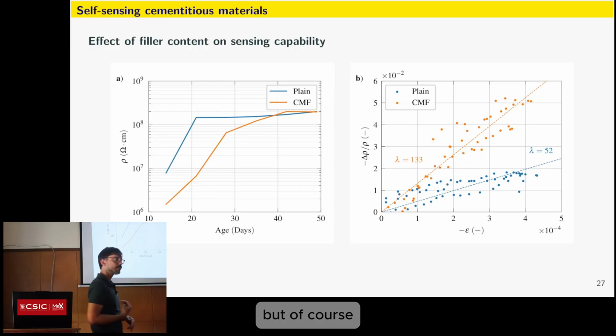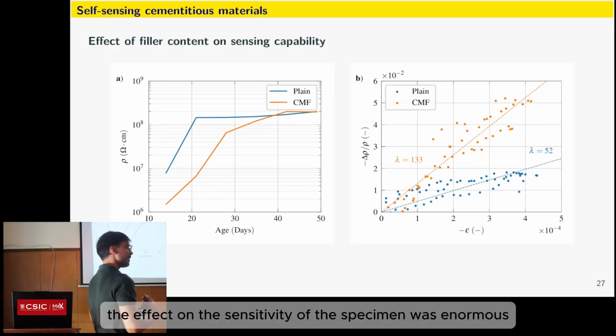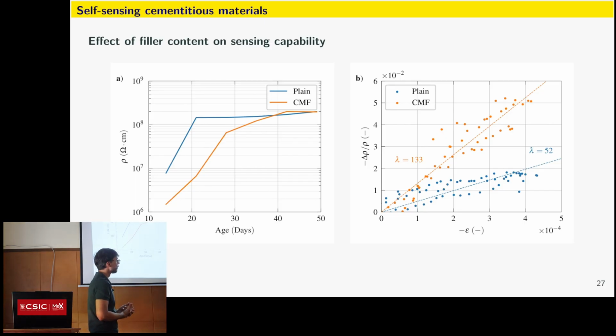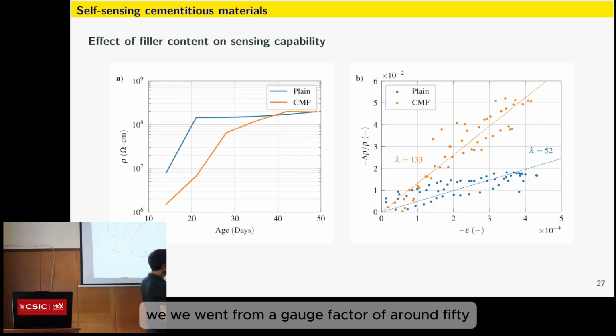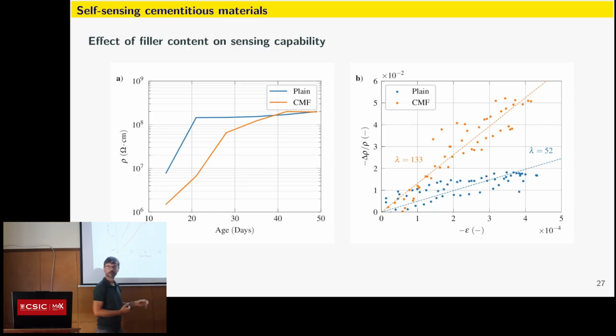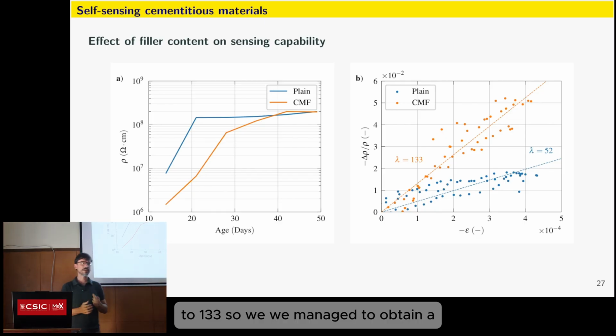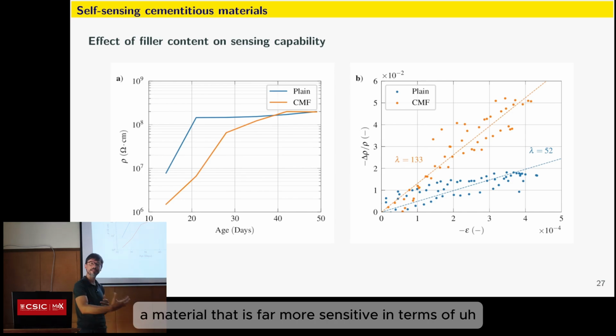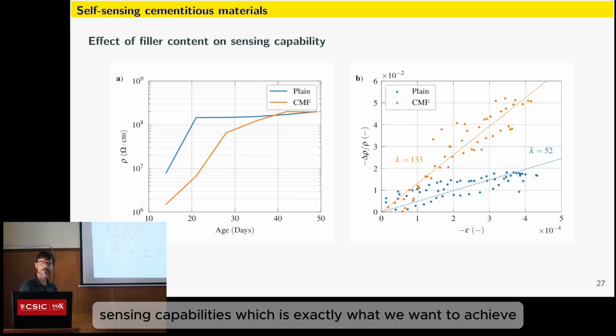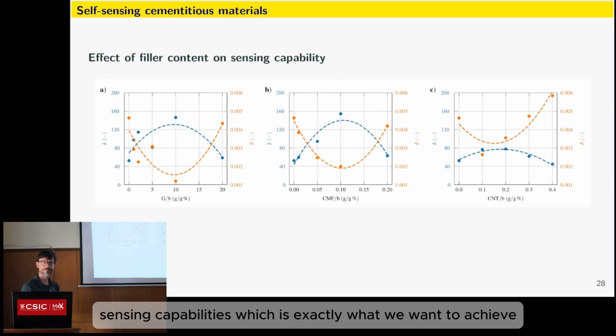But of course, the effect on the sensitivity of the specimen was enormous. We went from a gauge factor of around 50 to 133. So we managed to obtain a material that is far more sensitive in terms of sensing capabilities, which is exactly what we want to achieve.